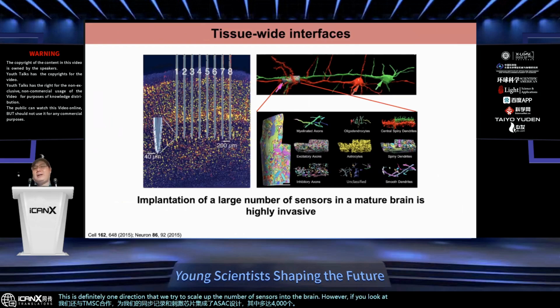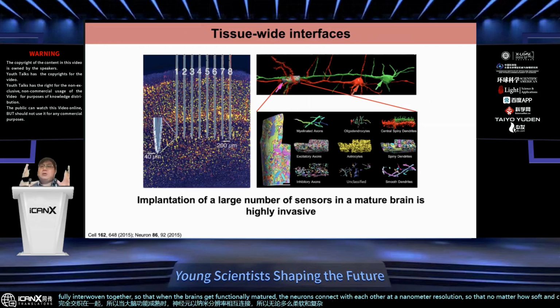However, if you look at the brain architecture, for example, this is the beautiful work done by my colleague, Professor Jeff Lichtman at Harvard. They used EM to scan the 3D connections of neurons in the fully matured brain. You can find that when the brain gets functionally matured, even in this tiny region, 20 times 20 times 40 micrometers, there are hundreds of different cellular components that are fully interwoven together. So when the brain gets functionally matured, the neurons connect with each other at nanometer resolution. No matter how soft and how flexible you design those devices, as long as you implant them into a functionally mature brain, you need to break the neural connectivity at nanometer resolution. So this is a kind of acute damage that cannot be avoided.